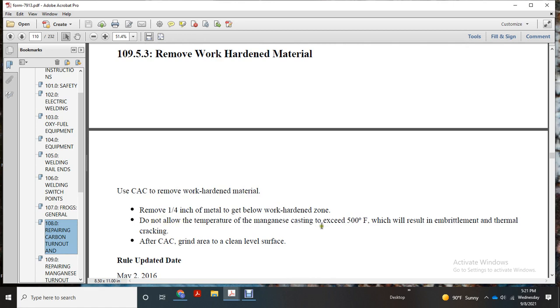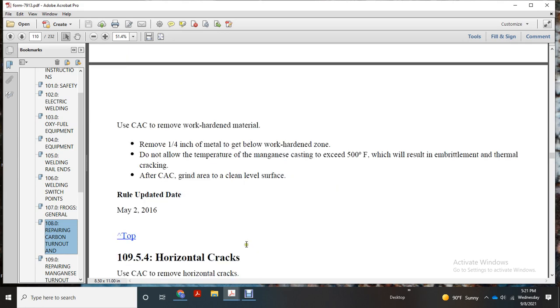Do not allow the temperature of manganese casting to exceed 500 degrees, which will result in embrittlement and thermal cracking. Use carbon arc cutting and grind the area to a clean, level surface.